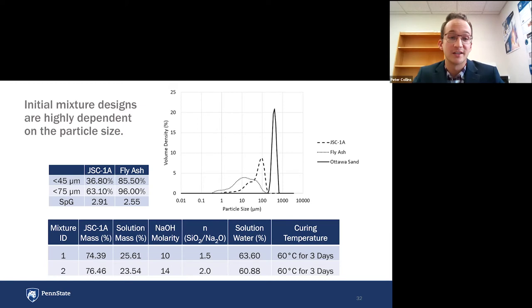63% of the JSC-1A is finer than 75 microns. And depending on your cement, that can be the typical cutoff for cement fineness. And so that is what I am assuming to be the binding component of the JSC-1A, as the larger particles, as we also saw, are less reactive. Because such a high percentage of the JSC-1A is finer than 75 microns, it's significantly increased my solution mass right now. So you can see in the bottom table, two mixtures that I've tried where the JSC-1A is roughly 75% and the solution mass makes up about 25%.